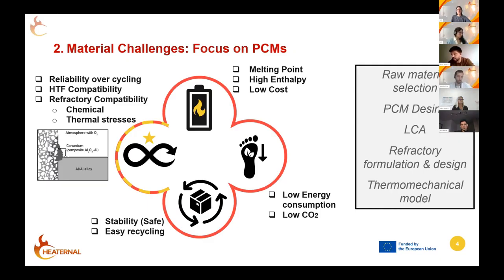But I would like to particularly highlight the challenges related to the lifetime of the system. First, the reliability of the PCM during thermal cycling. The PCM must maintain the initial thermal properties over many thermal cycles. It must also be compatible with the heat transfer fluid, which in this case is air. This makes oxidation processes critical since we are working with metals. And finally, the PCM must also be compatible with the refractory materials, both chemically and in terms of thermal stresses derived from the different thermal expansions of both materials.